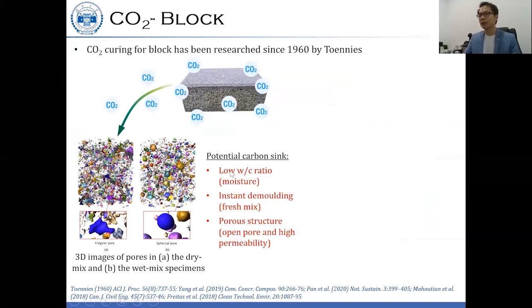Why? So first, we know that concrete block is prepared with relatively low water to cement ratio, so that we can compact and have instant demolding feature. And at the same time, we have a higher porous structure. And during this situation, we are still able to provide sufficient moisture. And at instant demolding, we have a fresh mix for concrete or alkaline solid waste material. And before it hardens, we have an open pore structure, which has a high permeability for the CO2 gas diffusion. So this could be almost the very ideal condition for CO2 reactions.